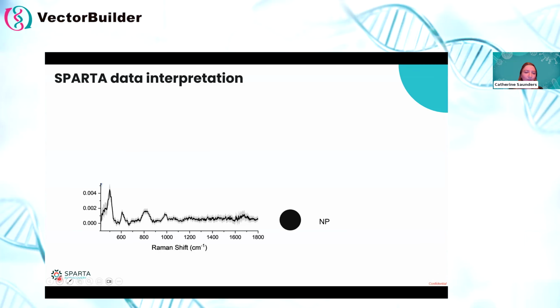So now, with all of those promises, I'm going to introduce some SPARTA data to explain how we can access this information. What I'm showing you here is the Raman spectrum from a pristine particle. So this is an average spectrum. It's made by averaging all the individual particles that are measured in a sample. So you can see there's a solid line, that's the mean line, the average line, and the shaded region is the standard deviation.